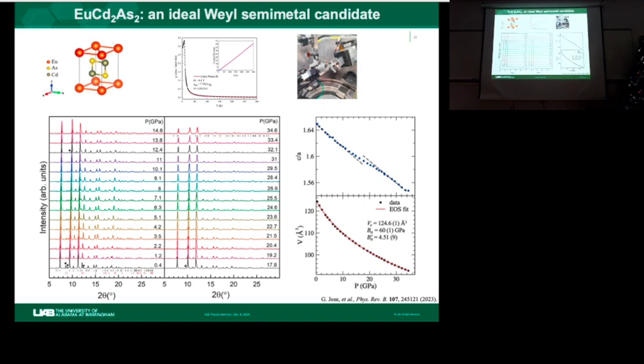So, because the magnetism on europium is closely related to the valence state of europium, how many 4f electrons are in there, and also the crystal symmetry is critical to achieve the predicted topological state. So we first look at how the crystal lattice is changing under high pressure. We took X-ray diffraction data to keep track of possible crystal structure transitions, and we found that even to 34 GPa, the trigonal crystal lattice is still maintained. Although when we plot the c/a ratio, the axial ratio, and the volume, we clearly see an anomaly in the c/a. However, we don't see anything in the volume, the equation of state.